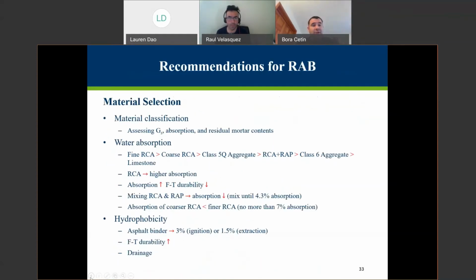So, material selection that Raul mentioned: of course, not everybody will have a chance, or there may be time constraints, to do all these tests on each test section. So especially during the design stage, how can we predict, how can we select the appropriate materials? We came out with assessing specific gravity, Gs value, absorption and residual mortar contents of RCAs as very important information, and looking into the water absorption characteristics. So maybe put some limits on the absorption characteristics.